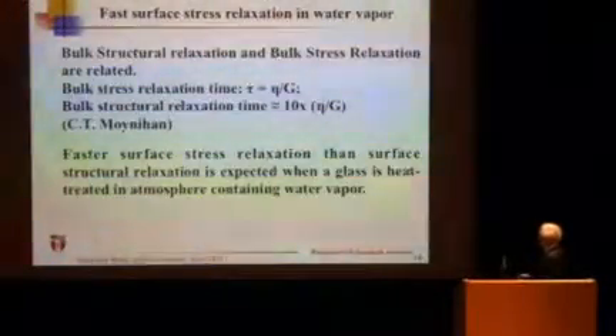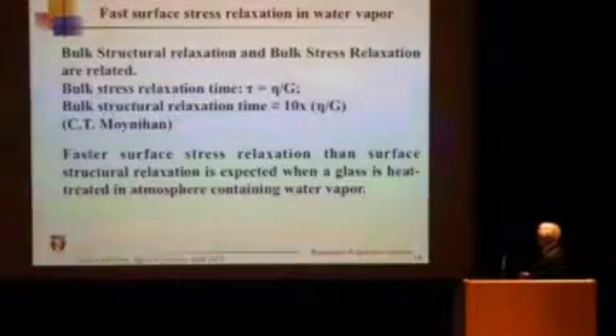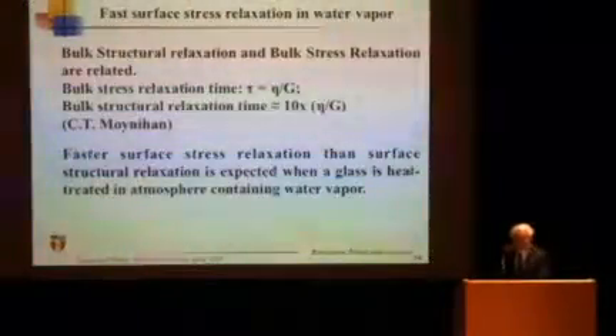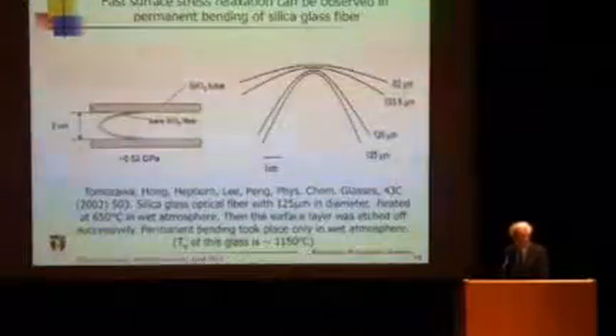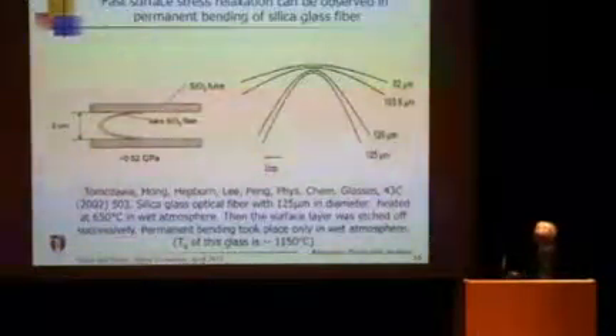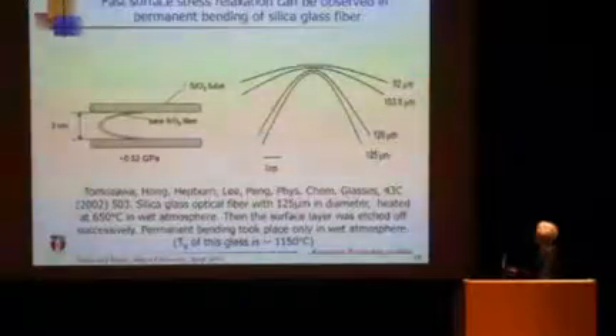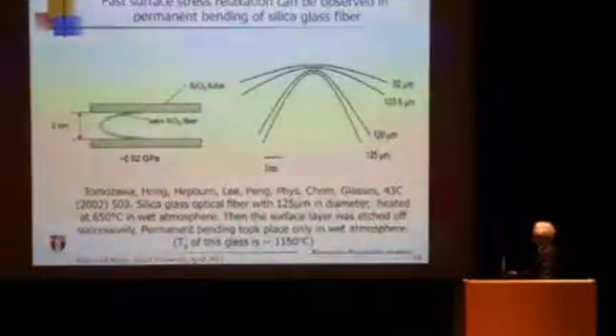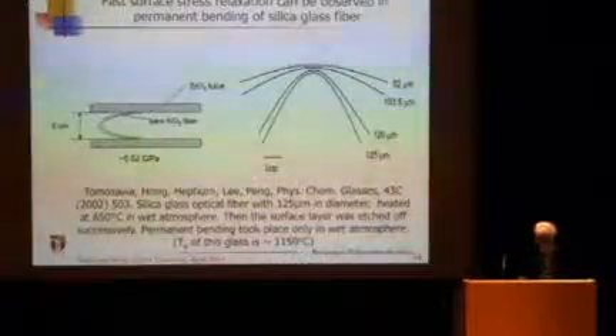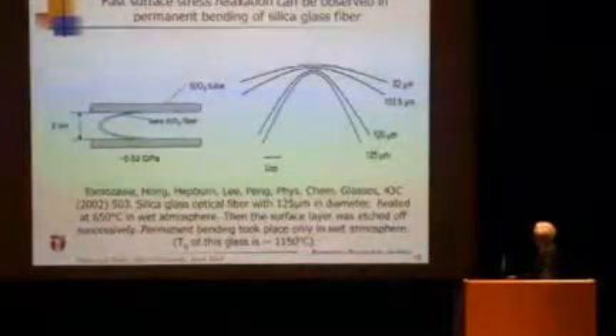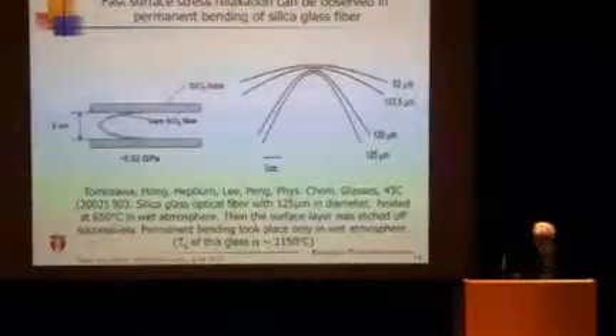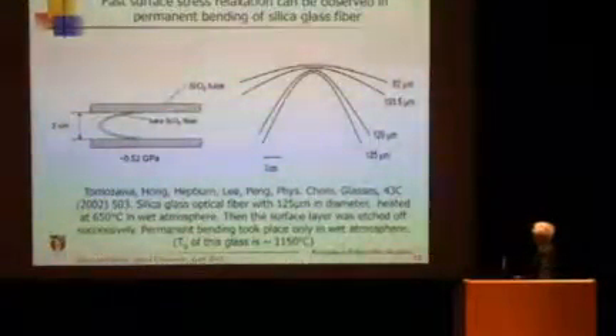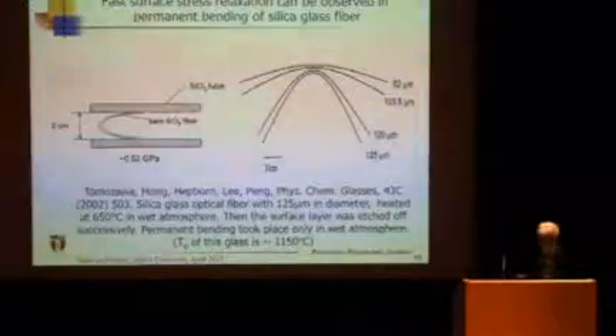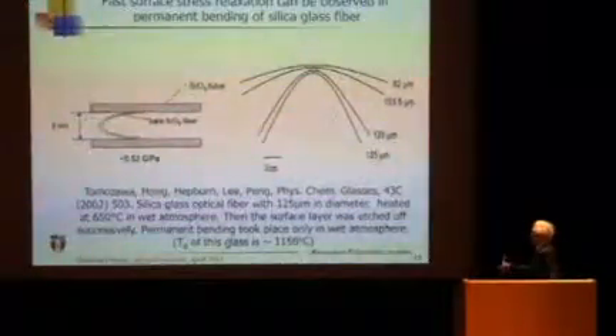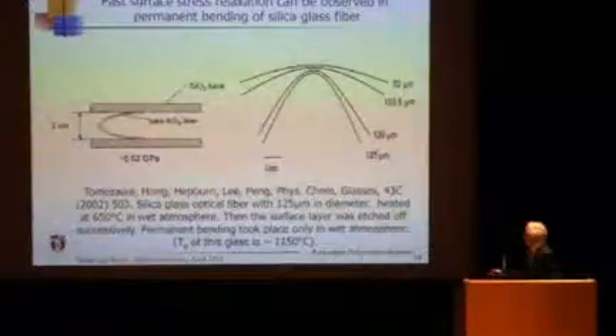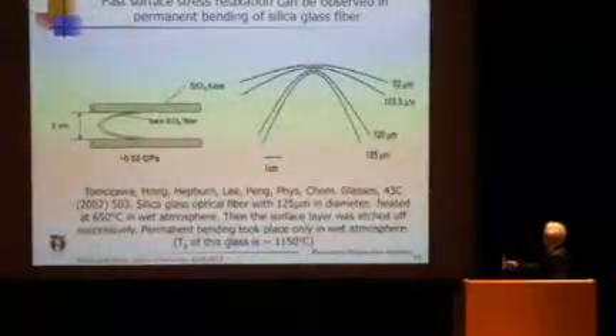And what we found is that the surface stress relaxation also changes faster than bulk. What we did was we took a silica glass fiber, held it in a silica glass tube and kept it at 650 degrees for a couple of hours, which is 500 degrees below the glass transition temperature. Tg is 1150. So nearly 500 degrees below the glass transition temperature, and then we took this out of the tube.